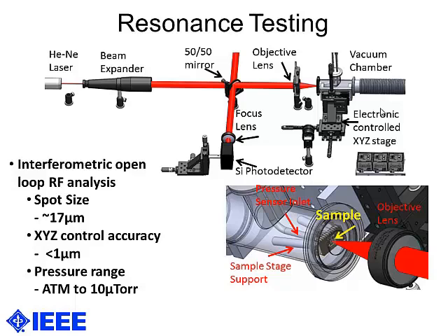The system runs with a spot size of approximately 17 microns, which is much, much smaller than the diameter of our membrane, allowing us to do mapping across the membrane with the XYZ control stage of less than a micron accuracy. And we ran it with a pressure measured in the range between atmosphere to 10 microtorr. The majority of these tests were done in the low millitorr, high microtorr range.